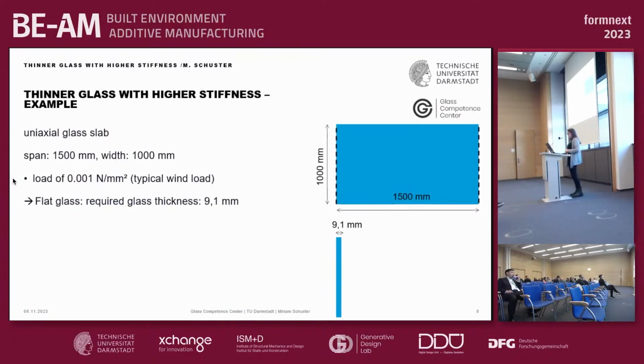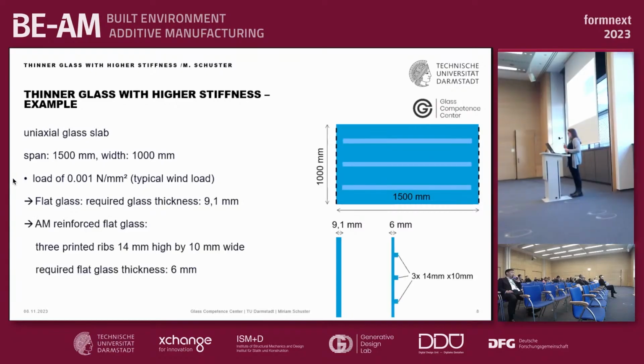Here we have one very specific example. This is a glass plate with the dimensions of 1.50 meter by 1 meter. And we have a linear support at the shorter sides, so the span is 1.50 meter. In order to fulfill the serviceability limit state according to the German standard, we would require a glass thickness of 9.1 millimeter, which actually is not a standardized thickness for glass, so we would even go for the 10 millimeter thick glass. However, by modifying these glass sheets with only 3 reinforcements with dimensions of 14 millimeter by 10 millimeter, we could reduce the thickness of the glass plate to 6 millimeters, which is huge, since this means that we have a material saving of approximately 30%, which also means that our structure is lighter, which is very advantageous for the transport and also for the installation.